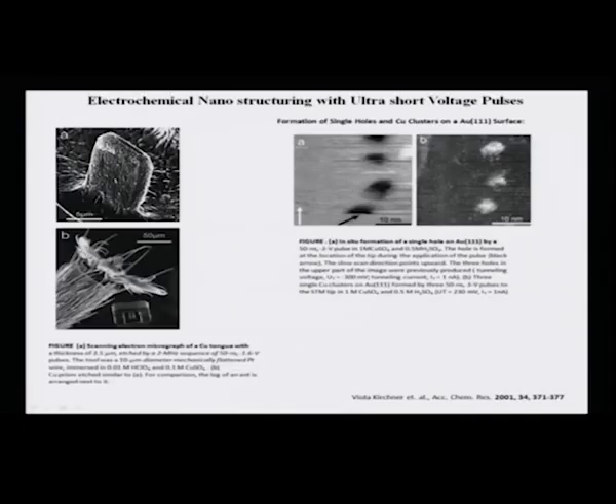ECMM is also applied in this particular case where ultra short voltage pulses are again used for obtaining this copper tongue, for example. This is an SEM image of this copper tongue, and it has a thickness of close to about 2.5 microns. This is how small it is thickness wise. It's etched by a 2 megahertz sequence of 50 nanosecond pulses of magnitude 1.6 volts. The tool in this case is a 10 micrometer diameter mechanically flattened piece of platinum, and it compares very nicely to an ant leg. This right here is an ant leg, and you can see the scale is almost comparable in the SEM images above and below each other, which shows the process capability of the system. This is a 50 micron scale, this is a 5 micron scale, so about a tenth. That's about the comparison.